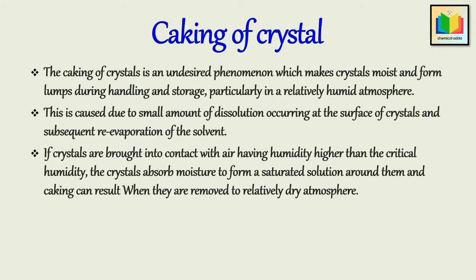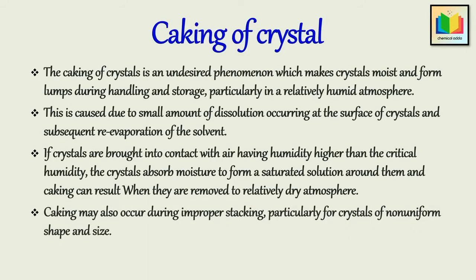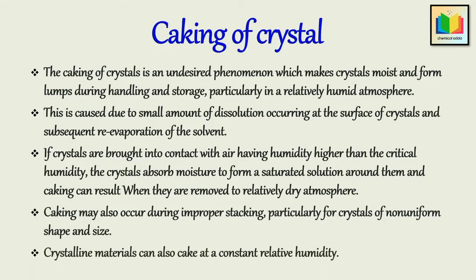Or due to subsequent evaporation of moisture, when the atmospheric humidity falls, the moisture re-evaporates and a number of crystals bind into a compact mass. Caking may also occur during improper stacking, particularly for crystals of non-uniform shape and size, because when the pressure at some points of contact becomes very high, the solubility increases, and on releasing pressure, the solution re-crystallizes and forms an agglomerate of several crystals.